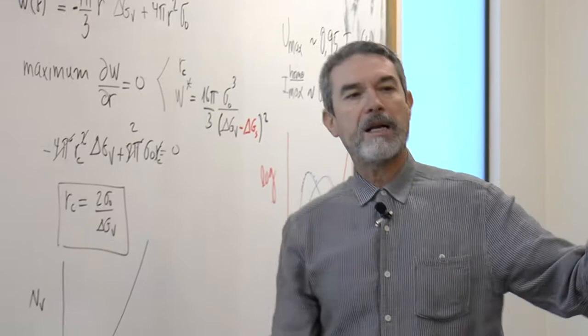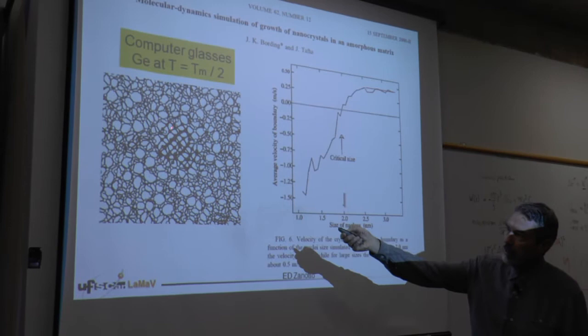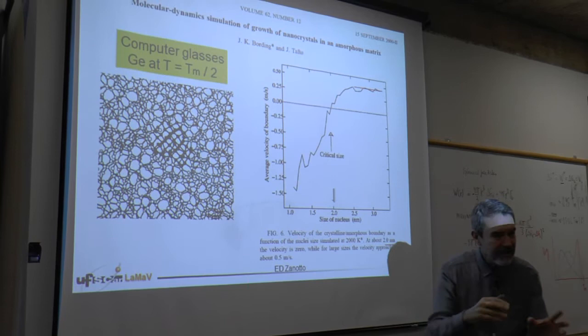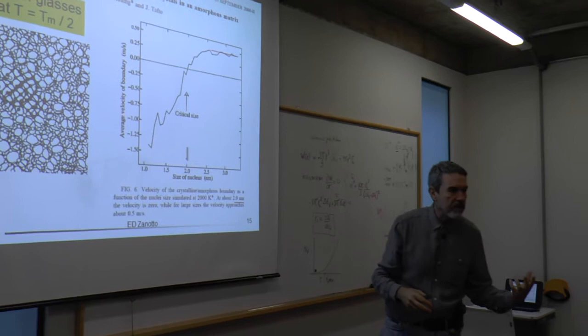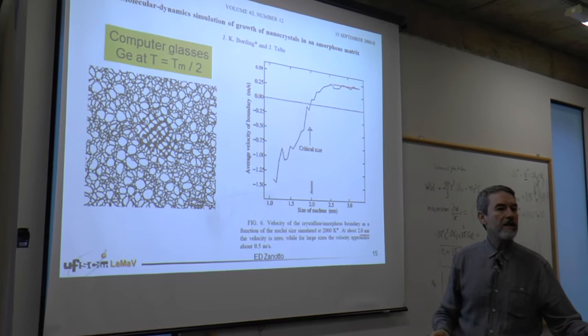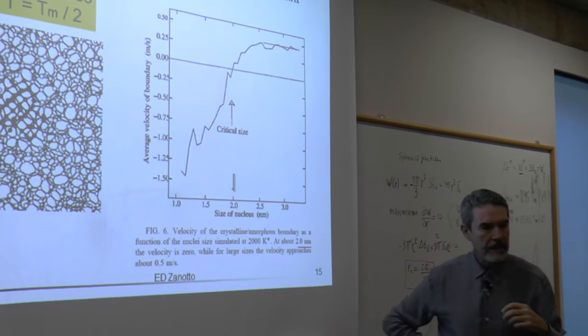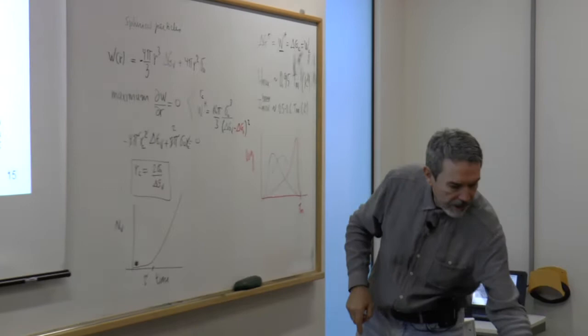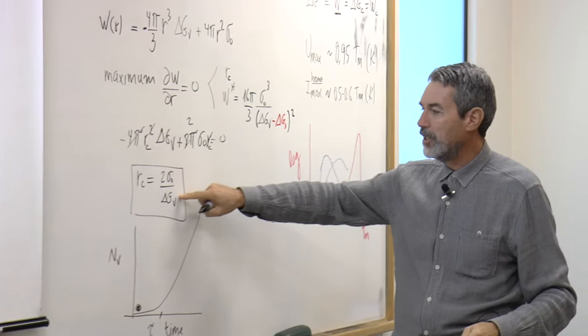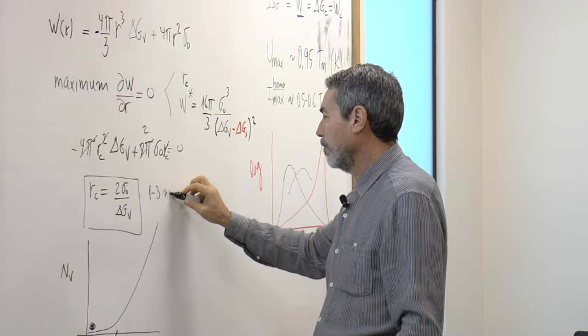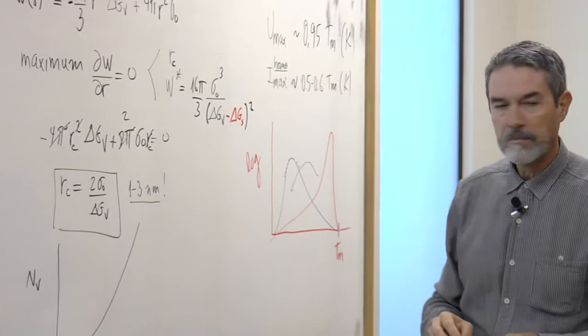They created, I'm not sure if you can see here, a nano-sized crystal in a vitreous matrix. So this is the liquid, with the ring size distribution and so on, all the features that we have discussed, but they created a nano-sized crystal here, and they varied the size. They created one with 1 nanometer, another one with 1.5, 2, 2.5, 3 nanometers. This is the kind of size that you normally get if you calculate the surface energy and delta GV at these undercoolings. The sizes that you get, from 1 to 3 nanometers, are calculated for the critical nucleus. So they did that.